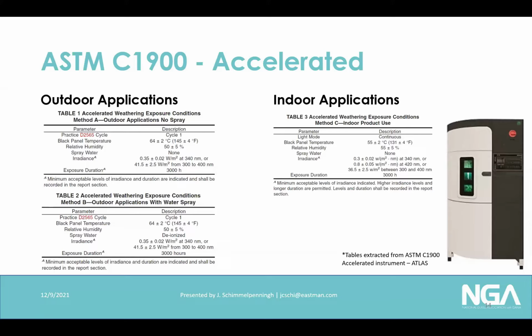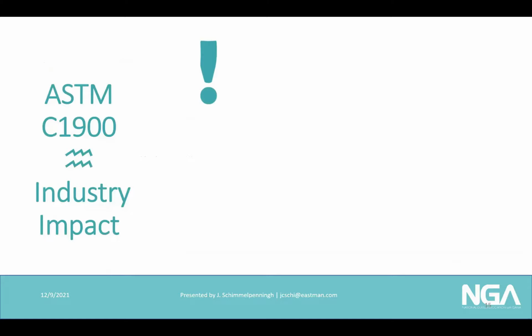When you choose a dry method over a spray method, I think the reason that the two of them are in here is currently ANSI Z97 requires the water spray. However, because of etching of the glass and the inability to get very accurate measurements, the dry method was put into ASTM as an alternative. And we can talk about how you do that as well.